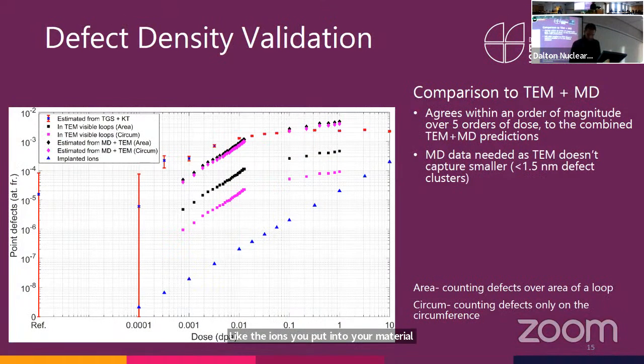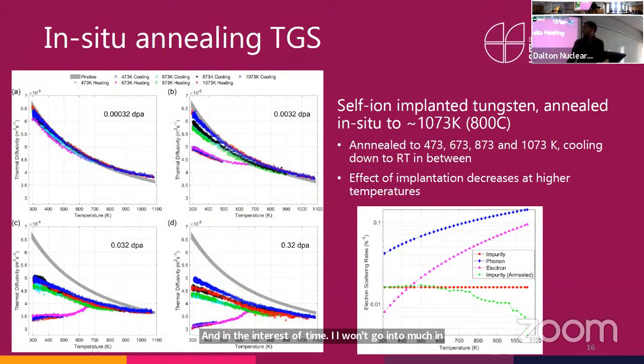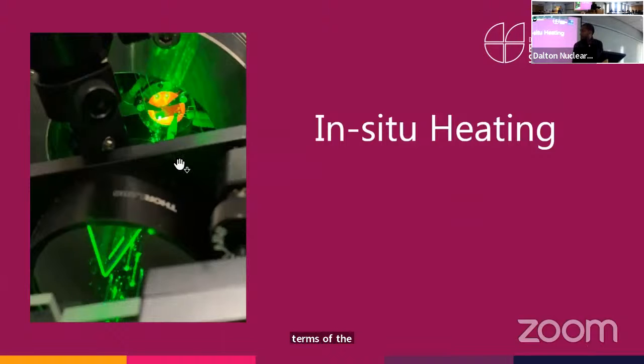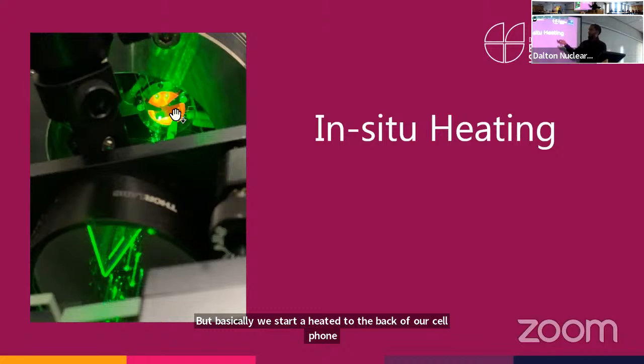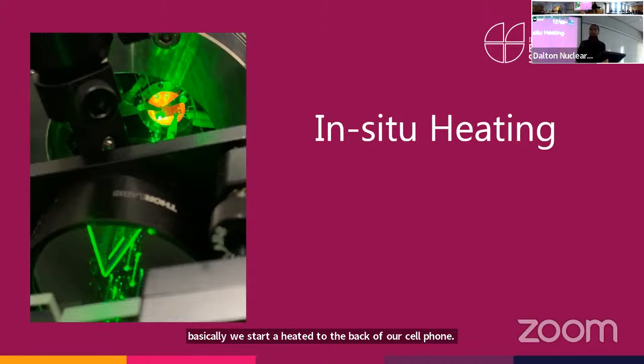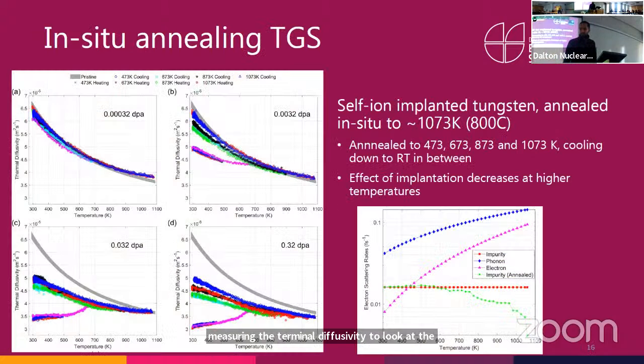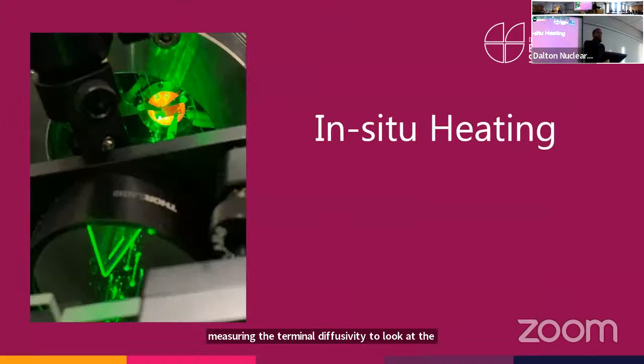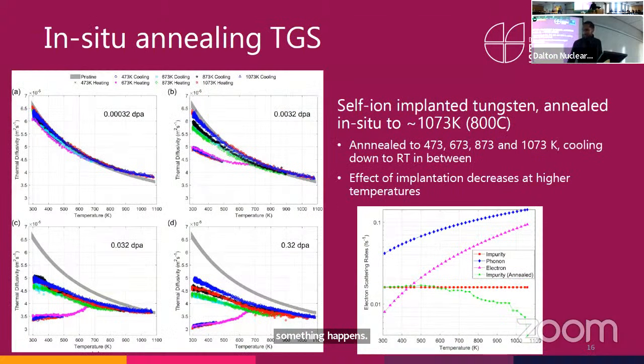In the interest of time, I won't go into much detail on the annealing work, but basically we stuck a heater to the back of our samples. So we were heating the sample while we were measuring the thermal diffusivity to look at the evolution of the defects and to see if anything would happen. I remember Felix telling me, okay, let's heat it and see if something happens. If something happens, then we have some research to do there. So yes, something did happen.